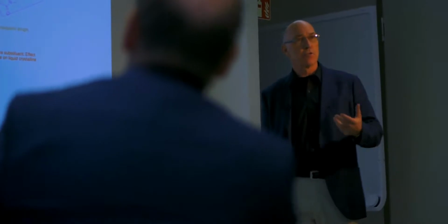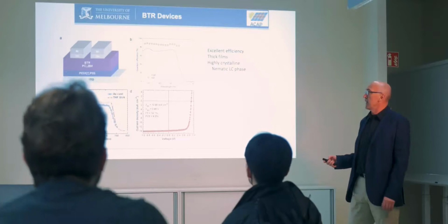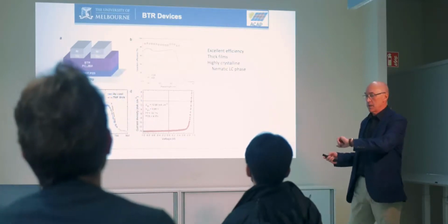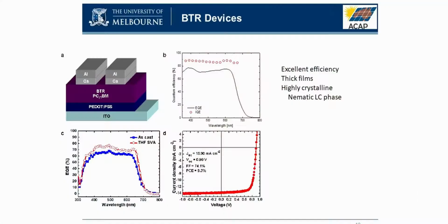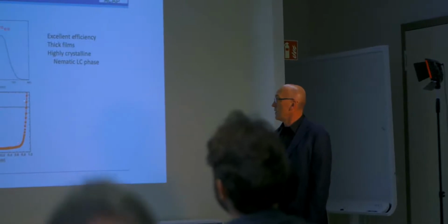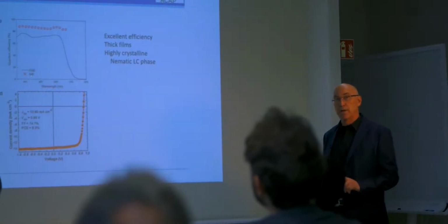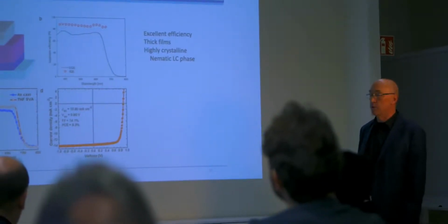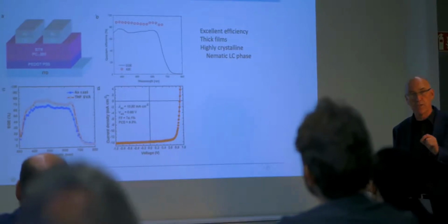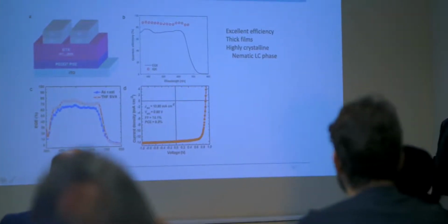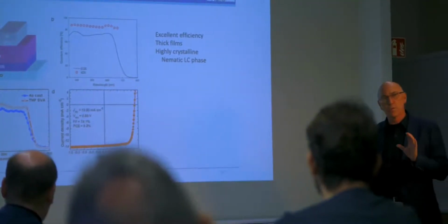And so we've had a lot of publications on this, looking at the structure, looking at how the structure evolves, looking at how then the devices perform. Okay, so very quickly, if we make a device, so we put this mixture of BTR and PCBM in here and make a simple device, we can then look at the efficiency of turning those photons into charges. And so as cast and then annealed, works okay. We get a reasonably good device here, and if we look at another device and look now at how efficiently we turn those photons into electric charge and get rid of all the reflections and everything else, we're getting about 90%, which is very, very good. And so these worked really well.